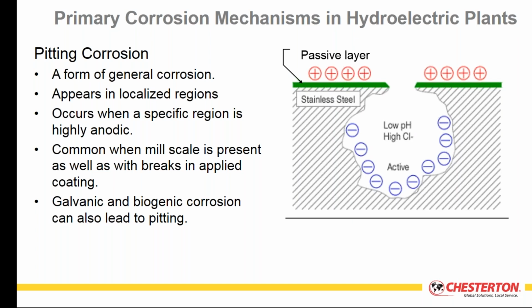If those oxide layers are removed by erosive flow, by impact, by mechanical stress, you have a small anodic region which is now exposed, and pitting corrosion will be initiated. There is an active ion transfer from the bottom of the pits to the top, and actually in those lower regions, the pH will be measured significantly lower than the pH at the top of the pit, and that will increase the electrolytic reactivity, which accelerates the corrosion cell.